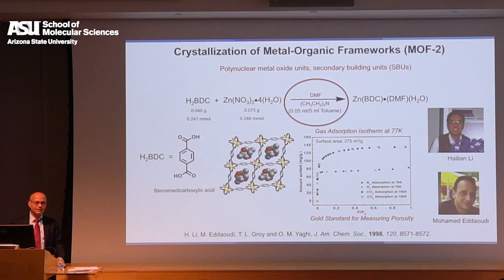Okay. So he went to the lab of Wagner. I think you remember Dave. Wagner had nanobalances that he used to use for catalysis to dose oxygen into his catalyst and measure how much oxygen using a nanobalance. So he interfaced the nanobalance with the Schlenk line type device and really measured the isotherm. This is the very first isotherm that showed to the entire community that metal organics could be made to be porous.